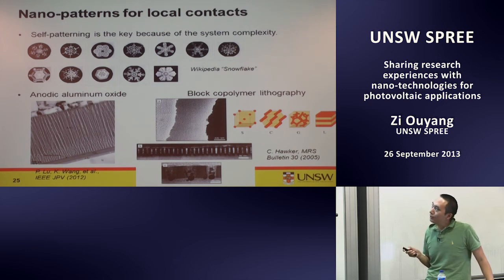But in nature, you can find self-patterning-like phenomena or methods, whatever you call them, everywhere. So this is a snowflake. You just change the temperature a little bit, change the pressure a little bit, change the conditions a little bit, and you can have tens of completely different shapes. That means you can have a lot of freedom to control the nanostructures at a microscale. One of the fancy and, I think, promising applications is that we're developing an AAO layer, which we find has a good passivation effect, and now we are researching the light trapping effect. My dream is that because it's a porous structure, once you can get metal through, you can make it a local contact as well.